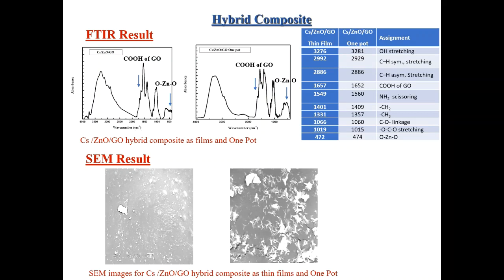Also, the scanning image for the composite prepared by the casting method showed white spots that accumulate in some regions on the surface. However, for the chitosan zinc oxide graphene oxide one-pot method, there are small white rod shapes and others that accumulate on the chitosan surface, which suggests that there are many interactions between chitosan zinc oxide and the graphene oxide edges.